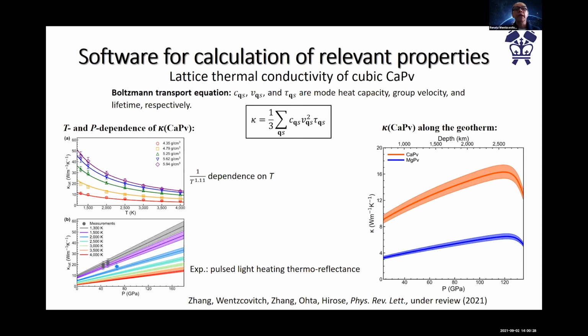This is a little tricky. For example, if you have the lifetime of phonons and the group velocities of these phonons that we obtain once we obtain the dispersions, and the phonon specific heat, we can calculate thermal conductivity within the linearized Boltzmann transport equation. And this is what we see here. Of course, lifetime for harmonic phonons is essentially infinite. We usually expect thermal conductivity to be smaller for anharmonic systems, especially systems such as calcium silicate, highly anharmonic. But what's surprising for us is that the thermal conductivity of calcium silicate is 2.5 times larger than that of magnesium silicate. Yes, the lifetimes are smaller, but the velocities are considerably larger.